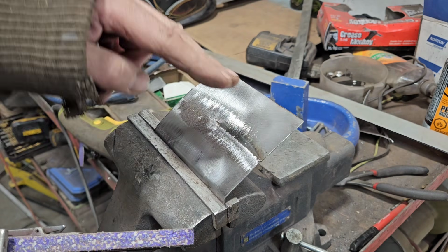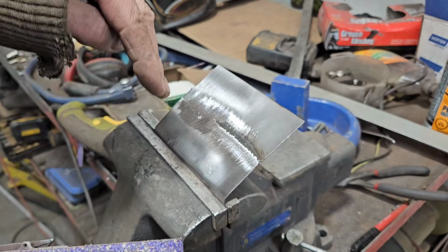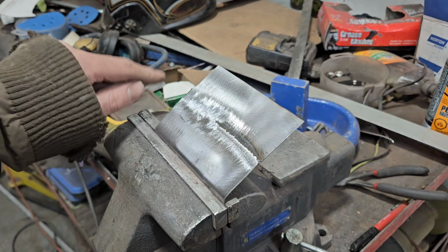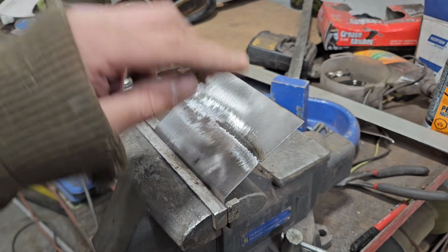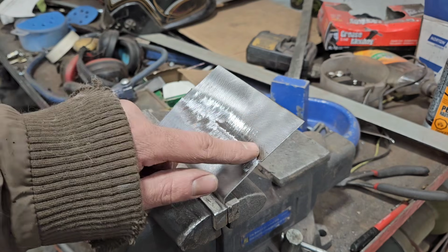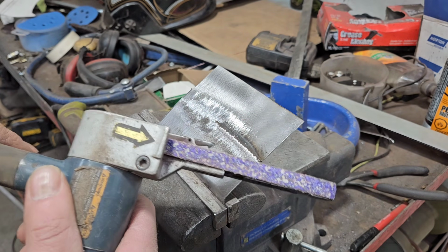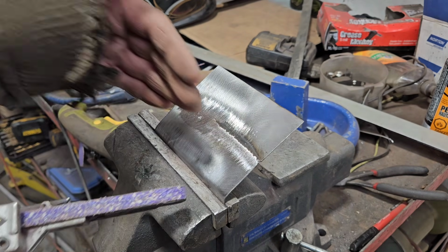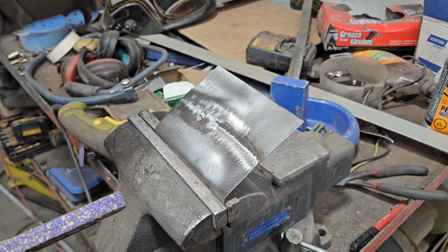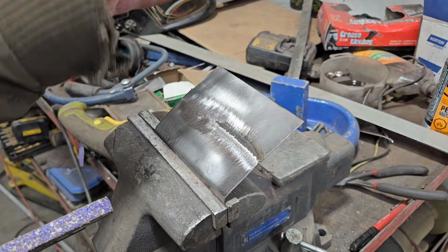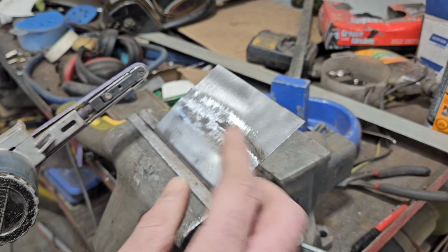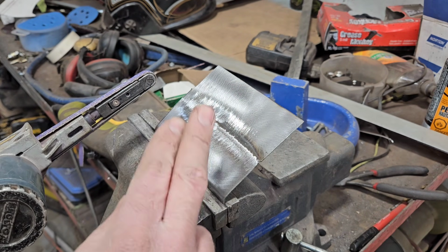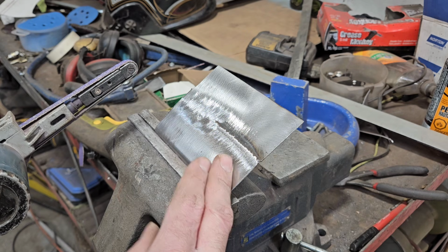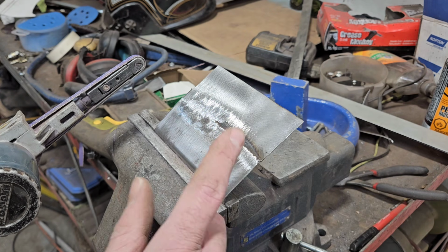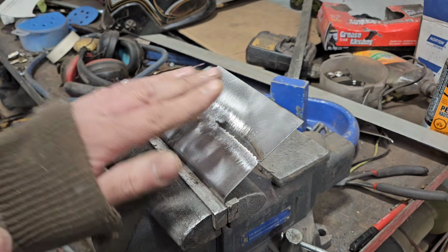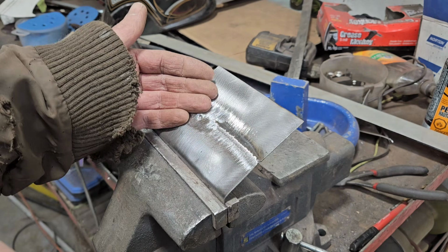Yes, you're only grinding the weld, but you're taking that away and creating a valley there, which is again going to weaken that joint. And I have seen it happen multiple times where a guy welded on a panel, ground it too heavily with one of these, and then the panel kept cracking. He had to keep redoing it, and it was a huge disaster. So if anything, grinding is more important than the welding itself because you can do an extreme amount of damage with a grinder. This is thin sheet metal, and it doesn't take much to thin it out to the point where it's now unrepairable.